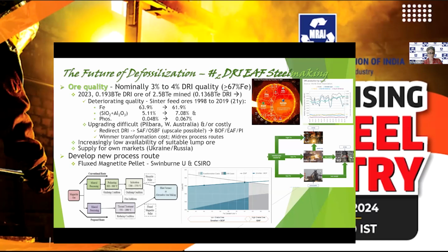Swinburne University and CSIRO in Australia have looked at this, and they've developed a pilot, well, actually a lab-based pilot, of fluxed magnetite pellets, which potentially reduce the cost of processing. It reduces it by one step, and it also does the magnetite processing at a lower temperature than normal. The graph in the middle there is just an example of the cost break even for the submerged arc furnaces and the electric arc furnaces below 67.5%. In this case, it's SAF, and above it's EAF.